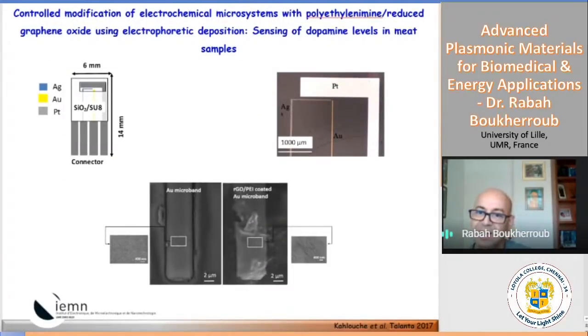The important part of this technique is that because I apply a voltage, the migration happens in an electric field. So I can really selectively modify a very small electrode, which is about 10 micron, in a microsystem. The whole microsystem here is about 6 millimeter by 1.4 centimeter, or 14 millimeter. And you see I have different electrodes. I have gold, platinum, and silver: the counter, reference, and working.